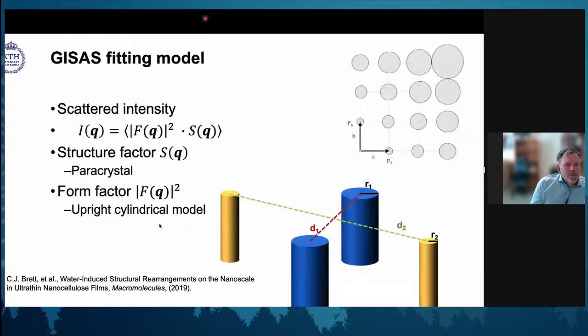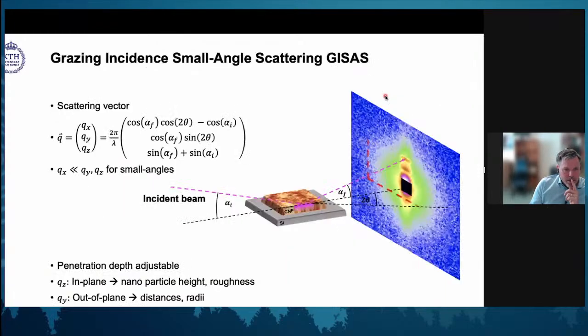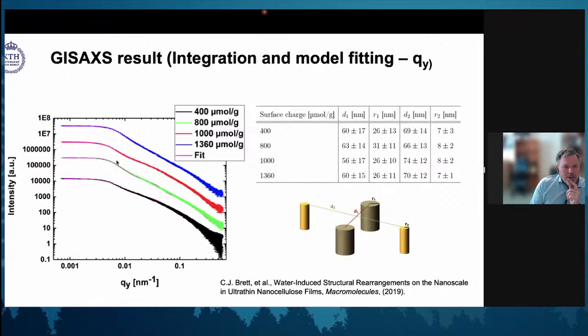Let's pretend that when the X-ray comes in, we can depict them all by having these cylinders, and we will choose to have cylinders of a couple of different sizes. So we actually determine that we have a cylinder of a given diameter, distance between themselves, and a different diameter with radius. So we can actually have a set of various sizes. And by doing the grazing incidence, we can take this model, we can fit it to the data. And again, we are fitting now the full field, the full image that we have here.